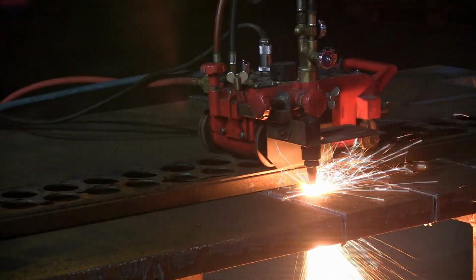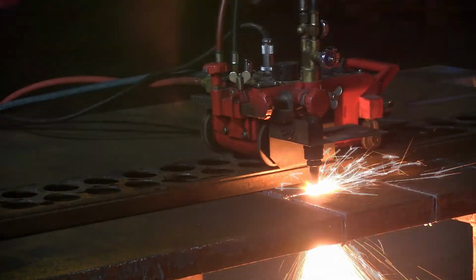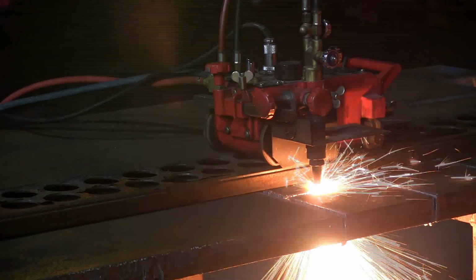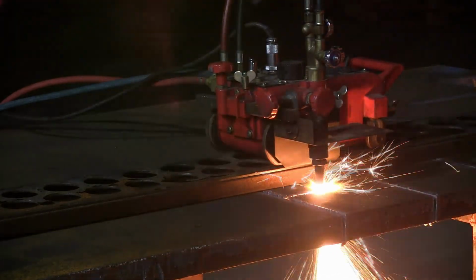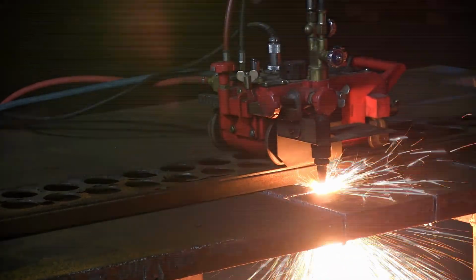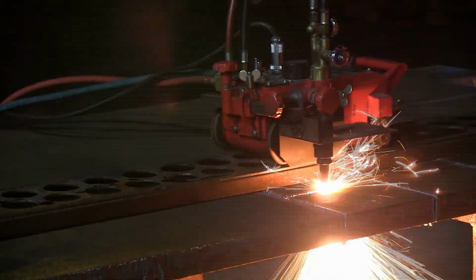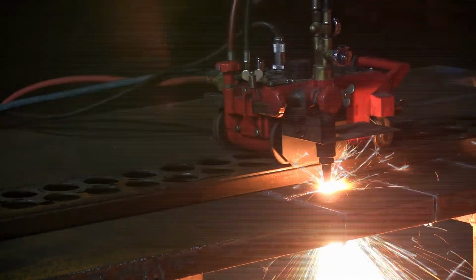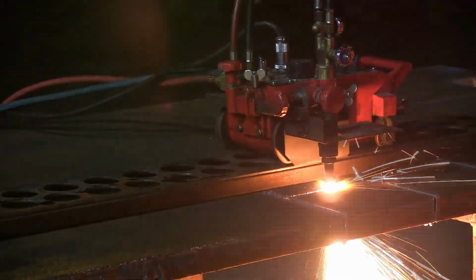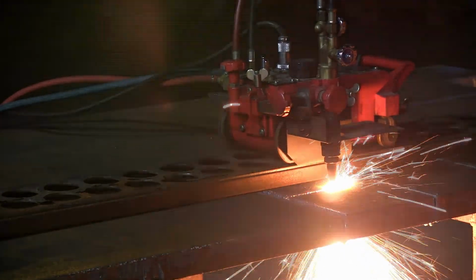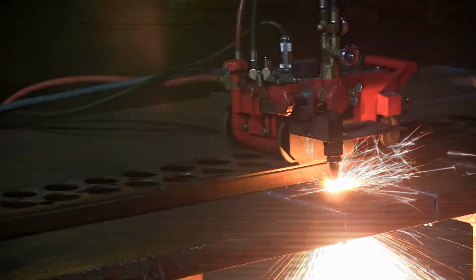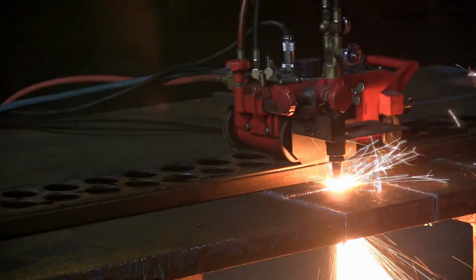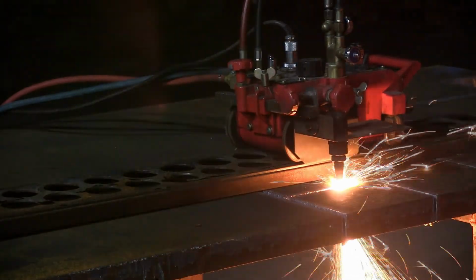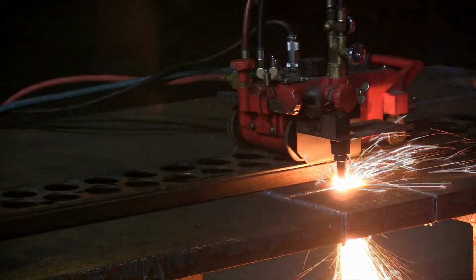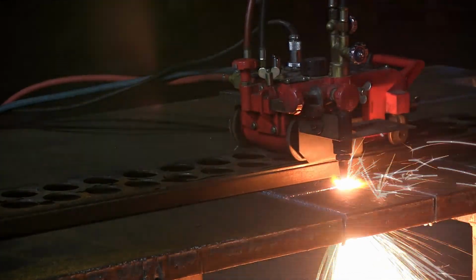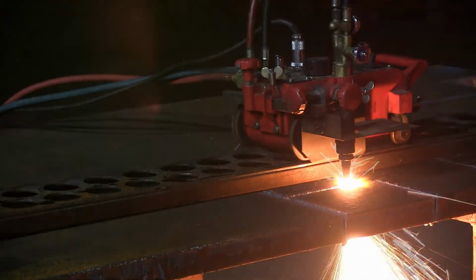You could probably go a little higher again with it if you set a stronger flame, but it will come to the point that the thickness of material will actually limit how well you will cut unless you preheat it, as I mentioned before, from the underneath. So then the material will heat up through a lot better, and you have a much cleaner cut. But at this speed, the cut that the machine does is pretty good, and it's well acceptable by any means.